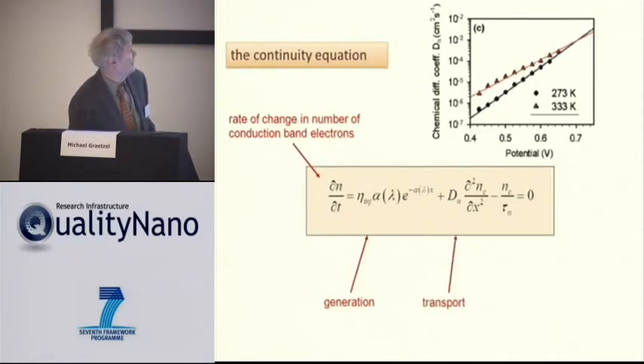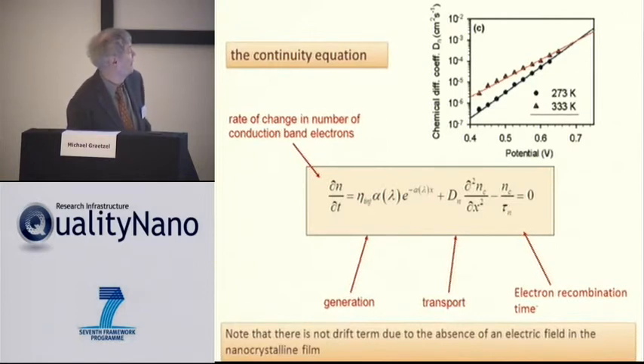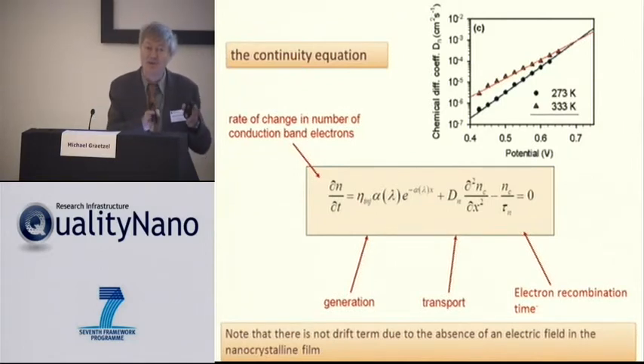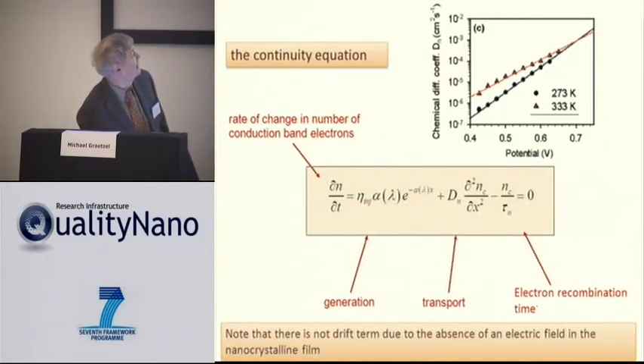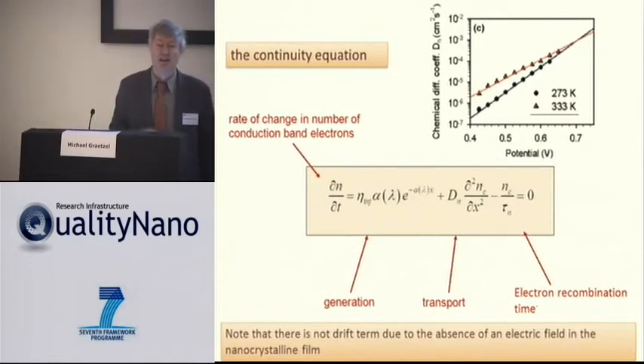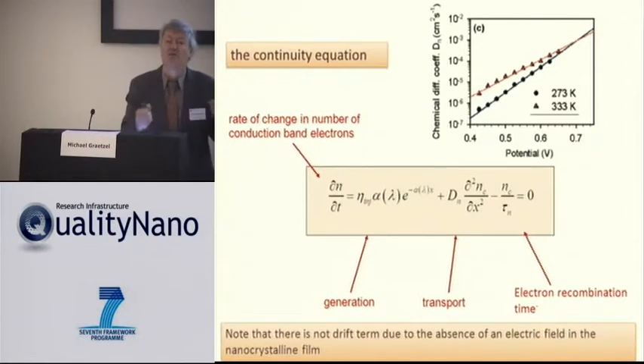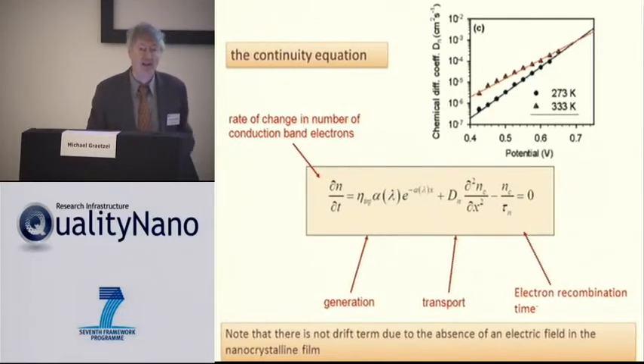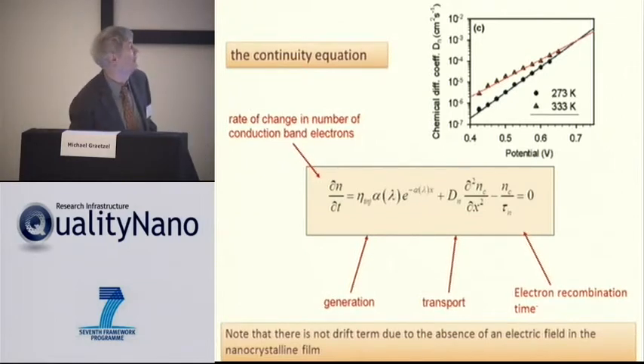And as I said to you, in the continuity equation there's no field, so no field term, no drift term. And I just wanted to mention to you that if we are at the open circuit voltage of the cell, in other words, you illuminate the cell, you have no current flowing, no leads attached, then of course there's no net charge collection and there's no diffusion really, so the generation and recombination terms are equal. That sets a very important criterion. You want to make sure that the charges you inject in those particles come out slowly. That's your loss term here. So if that's slow, then you can create a large voltage in the film, and that counts. Not only the current, the voltage counts very much so.